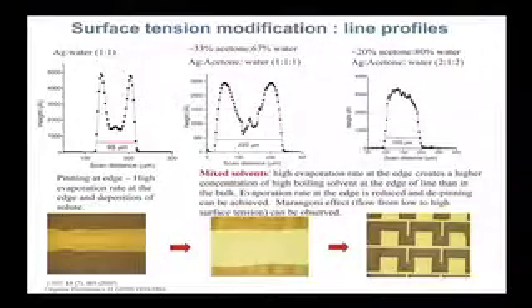And the coffee stain effect, the name comes from the rings that you get if you put a coffee mug on your desk and you spill coffee, you get a ring of coffee. So here is the same thing. When you deposit a drop on the substrate, you may achieve a condition where the drop is pinned to the substrate. And if the drop is pinned to the substrate, it means that as the solvent evaporates, the drop can't really shrink. So the drop is really pinned to the substrate.